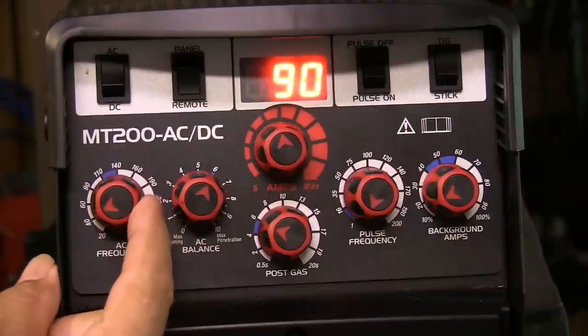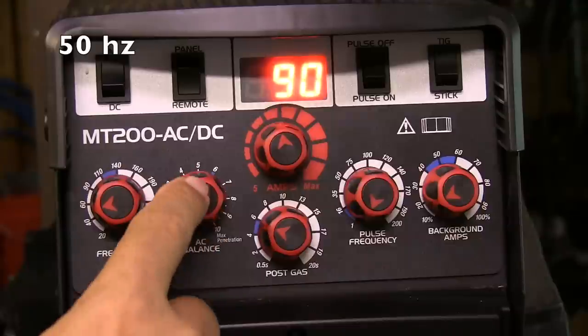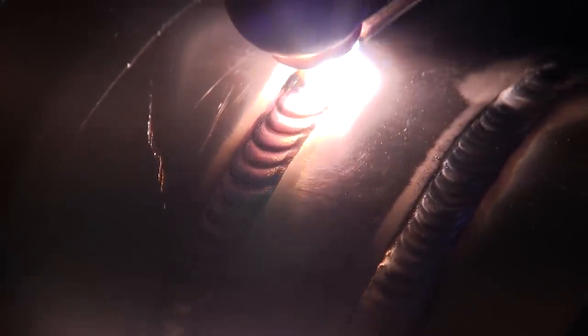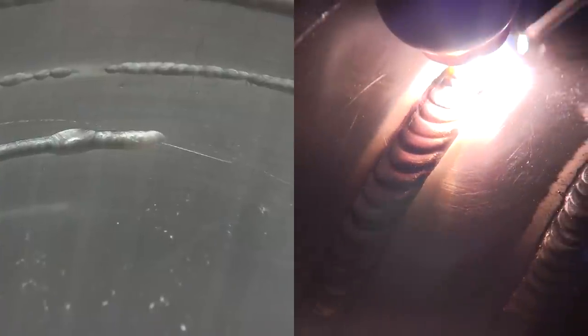If you leave the amperage the same, there's a definite difference in the amount of penetration that you'll get at a low frequency versus a high frequency. In my experience, the low frequency is going to get more penetration at a set amperage. Here, I'm at 50 hertz. I'm on a fixed rotator. This wall thickness is about 90 thousandths thick, if I remember right. And at 50 hertz, this is penetrating all the way through, no problem.